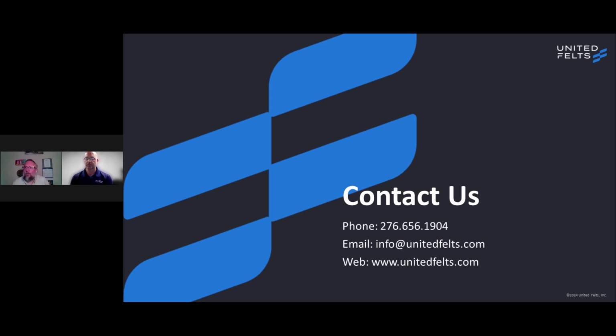Great. So considering EnviroCure for a culvert rehab, if there's no layer between the host pipe and the resin saturated felt, what prevents the raw resin from migrating downstream and potentially polluting a water body? That would be one of the applications where we would recommend the pre-liner to encapsulate the raw resin during the curing process. And then once cured, the styrene, for all intents and purposes, is captured or consumed during the polymerization or curing of the resin.